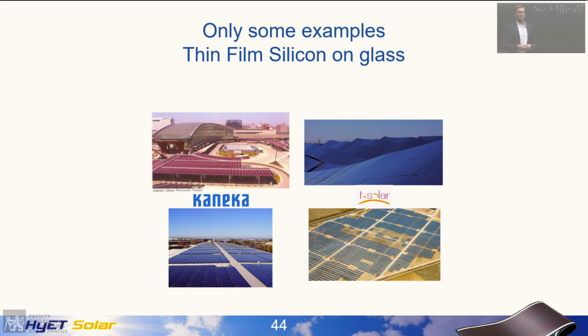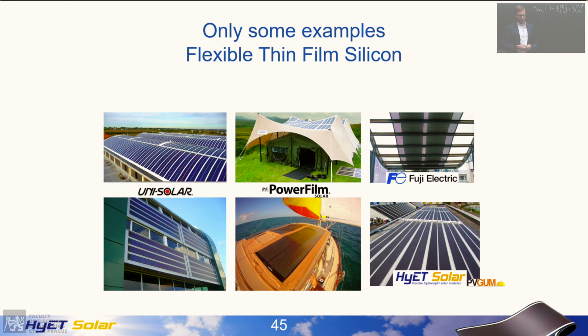So what is then a way to use thin film silicon? That is to make use of the fact that the absorber material is really very thin. We saw on the previous slide that the whole stack is only a few micrometers, compared to crystalline silicon wafers on the order of 150 microns nowadays. So there's really a very big difference, and it means that these devices are intrinsically really thin, and you can bend them. So several companies have tried to commercialize that in a flexible way.